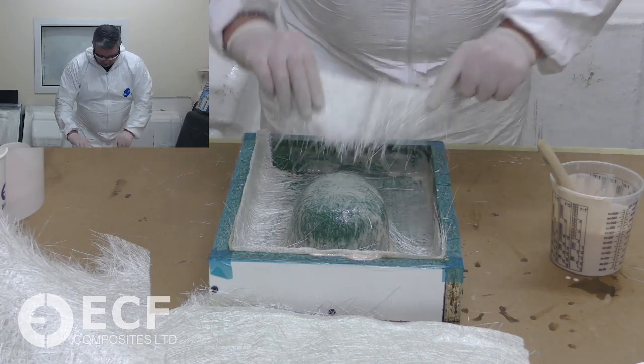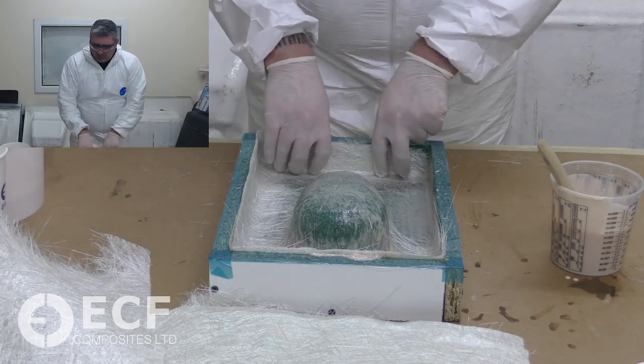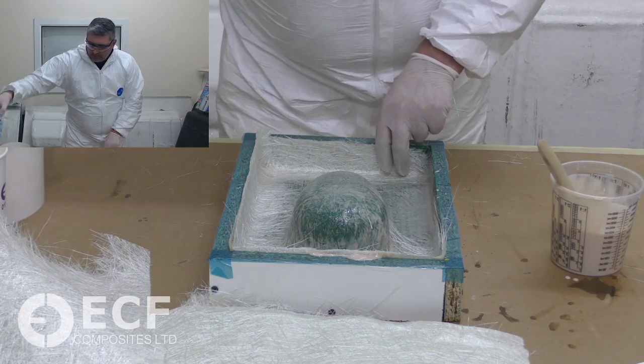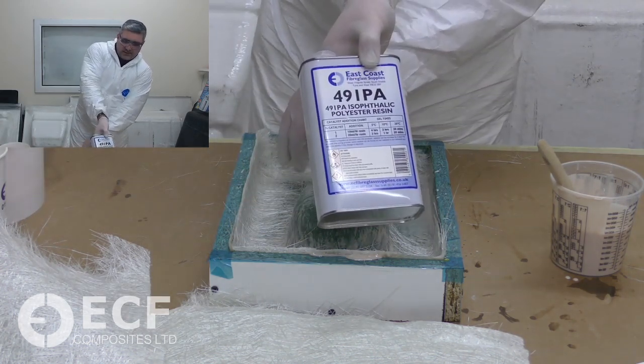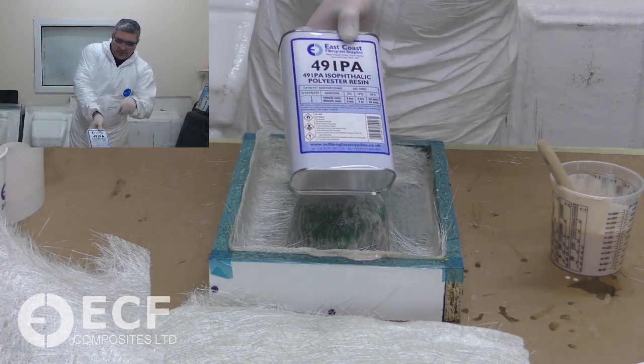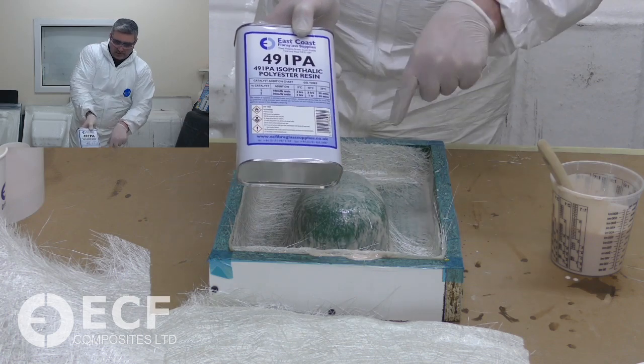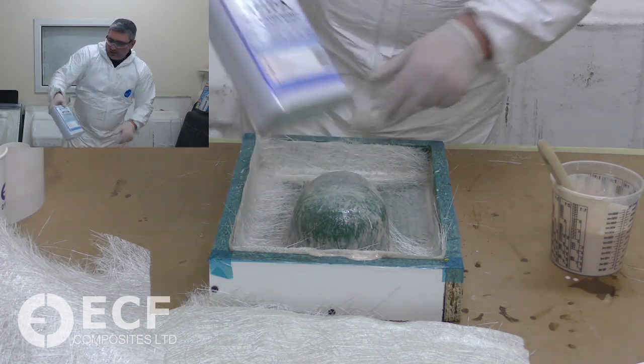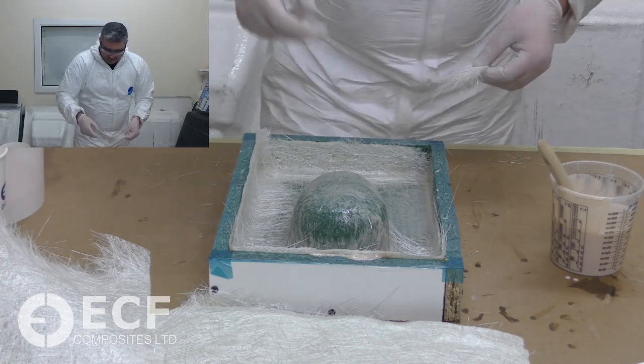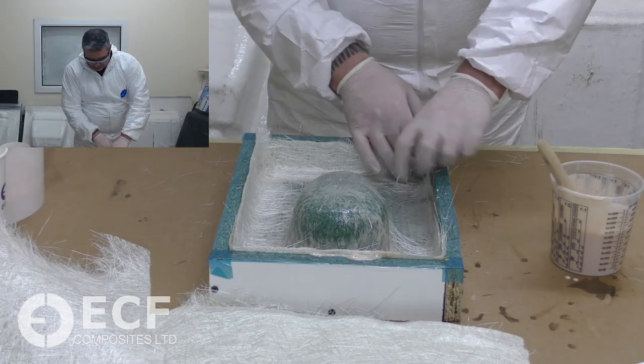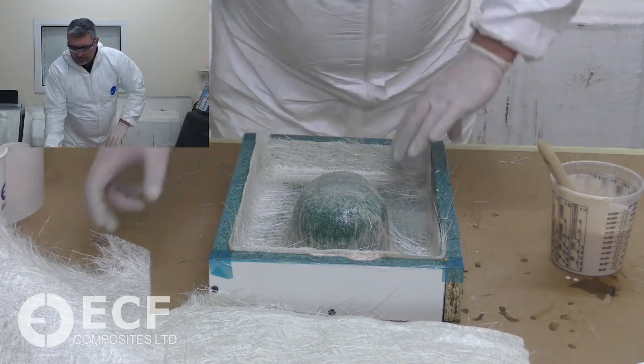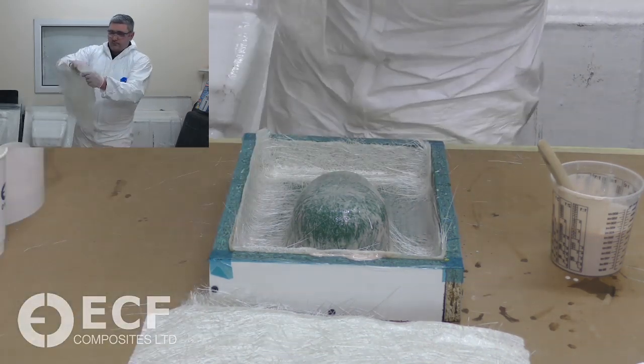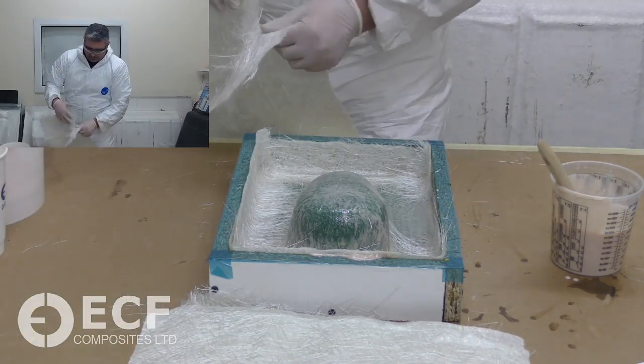What resin did you use for the first coat? That was 491 PA isophthalic resin, and that isophthalic resin bonds really well to the tooling gel, which is 15 PA, vinyl ester based. So you need that resin to get a good bond to that gel coat. Think of it as like a primer.